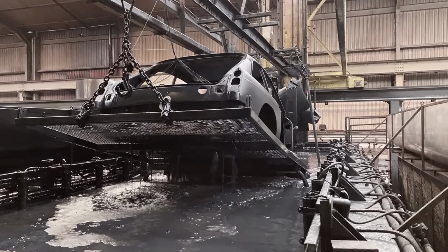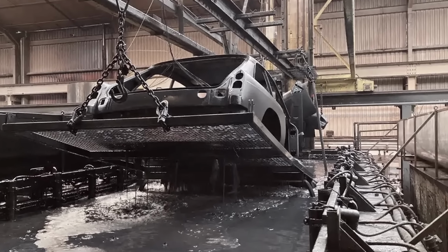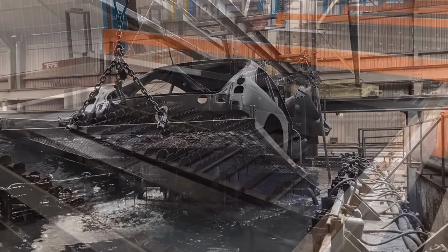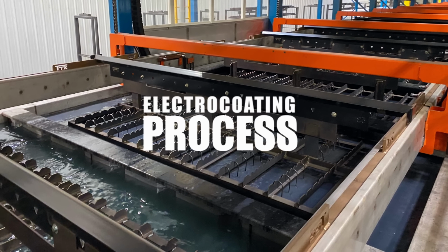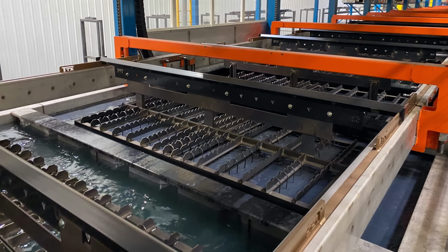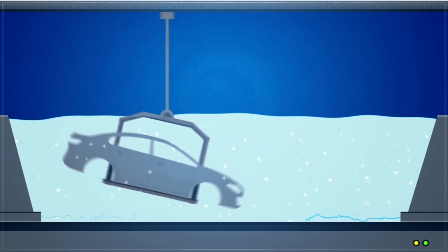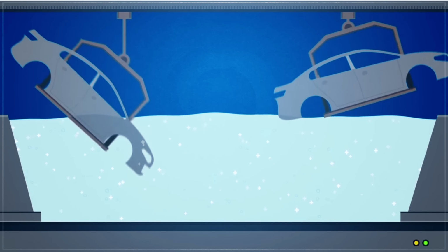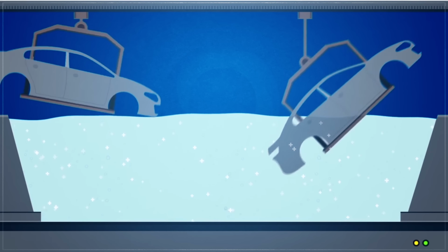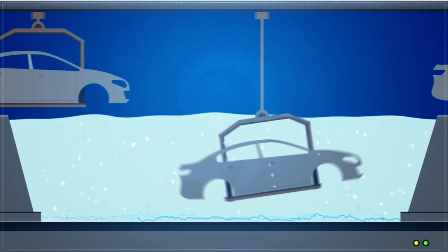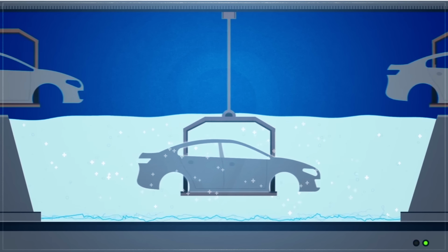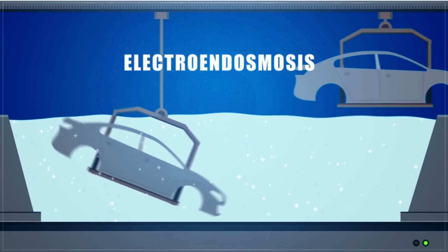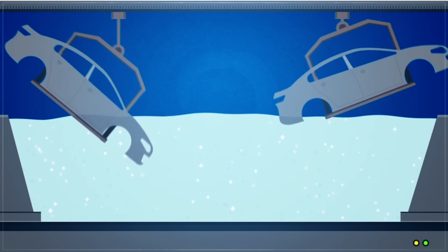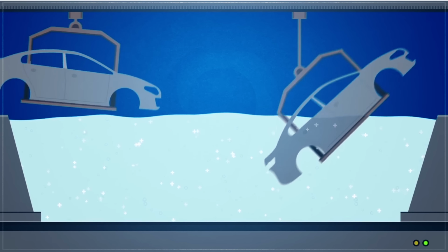In the 1960s, Ford Motor Company would pioneer a dramatically different approach to vehicle priming through electrodeposition. This groundbreaking technique, known as the electrocoating process, involves an aqueous dispersion of a coating carrying either positive or negative ionic groups. The car body is coated on the production line by immersing the body in a tank containing an aqueous primer dispersion and subjecting it to a direct current charge. This causes the dispersed particles to migrate to the vehicle body, with the transfer of electrons creating an electrically neutral film deposition on the vehicle's surface. As the coating builds, a process called electroendosmosis occurs, where water is displaced out of the deposited coating, leaving a firm surface. The body is then baked to coalesce and cure the primer film.